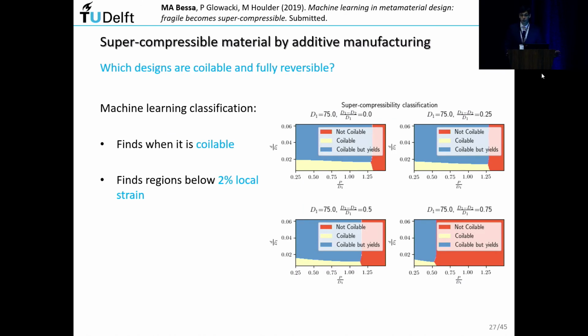So what's the goal? The goal is to transform this metamaterial into something coilable, super compressible, but reversible. We want to get back and do this over and over and over again. But now we know that the yield strain is about 2%. So what we did was very simple. The simplest possible yield criterion, maximum strain, and said, okay, if the local strain is above 2%, we classify this as coilable, but not reversible. So plasticity will start to occur and later fracture.